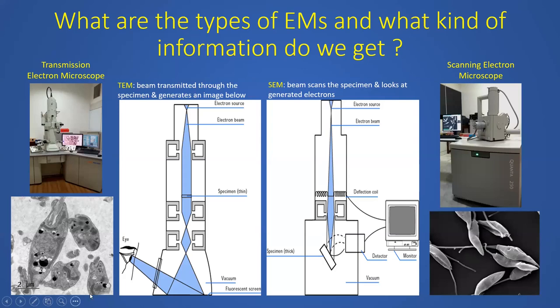So for a TEM, you are basically looking at very thin sections. You cannot have a very thick sample in a TEM because electron beams won't penetrate through the specimen. So typically, as Dr. Agarwal just explained, it has to be in the range of 40 to 80 nanometer and 100 nanometer thick specimen, for which you sometimes need to use an ultramicrotome for ultra thin sectioning, so as to obtain these very thin sections. So you need a very thin specimen for TEM, right? And you get a 2D image, 2D projection of the actual sample, which is on the left-hand corner here.